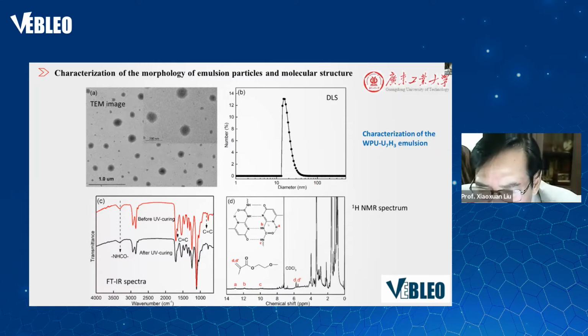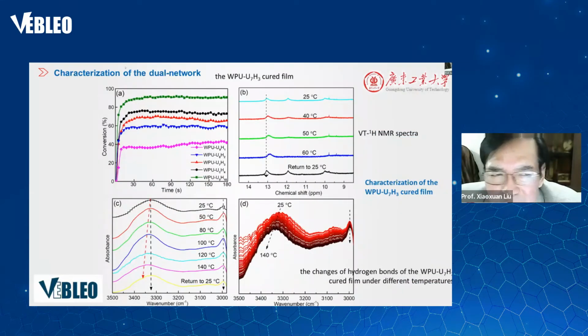So it clearly shows the multiple hydrogen bonds and the polyurethane structure. So the dual network characteristics. This is conversion. In figure 1C, we have different conversions, and with UV curing the conversion increased up to 90%, the green line.